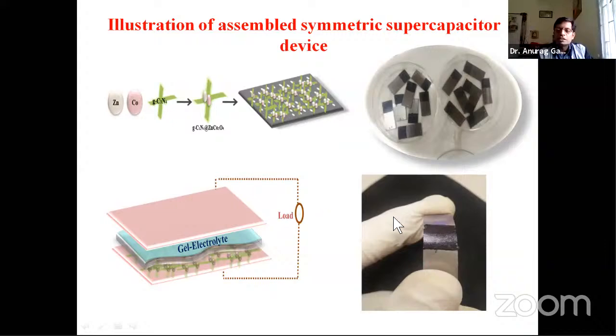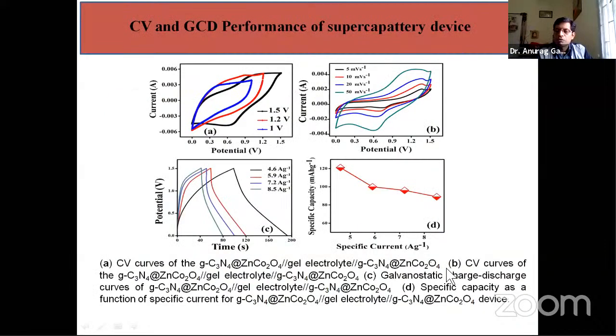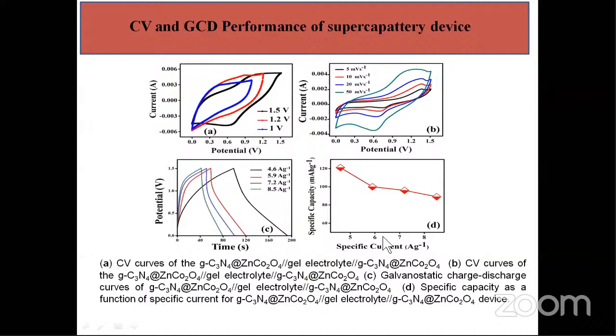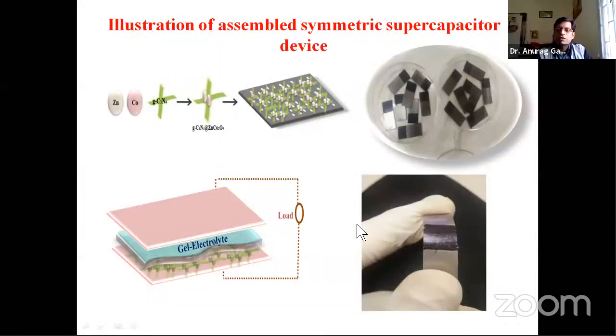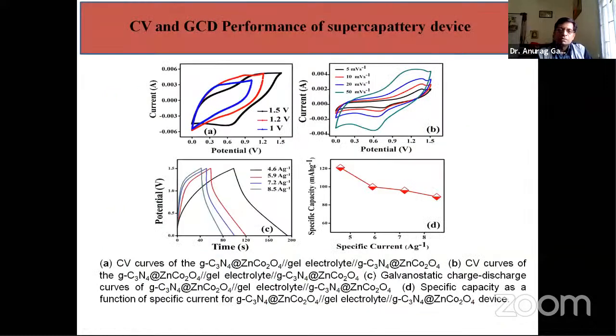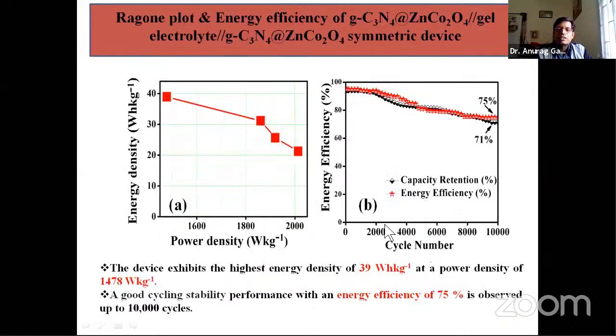And one thing is that it is flexible in nature. You can fold it in any shape. With this gel electrolyte concept, we can make this flexible structure. Then we tested the full cell. This is the full cell structure. This is the CV curve. This is the GCD curve. Again, it indicates that the material is pseudocapacitive in nature. And then energy density and power density are calculated.